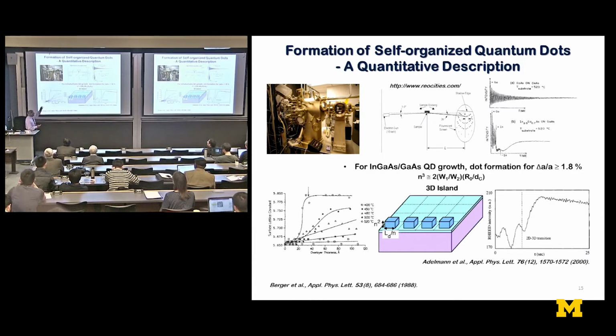One was, so we started growing indium gallium arsenide with different compositions on gallium arsenide, and we saw that the moment we open the indium shutter, after a few oscillations, the RHEED oscillations die. And this was not, as one or two authors had previously predicted, the critical thickness. All this was happening way before the critical thickness. And we knew this had to do with the three-dimensional growth modes in the pseudomorphic regime. And we predicted that in the pseudomorphic regime, the surface lattice constant will, instead of a step jump at the critical thickness, approach the critical thickness in a monotonic manner. And that's what we saw from the RHEED data.